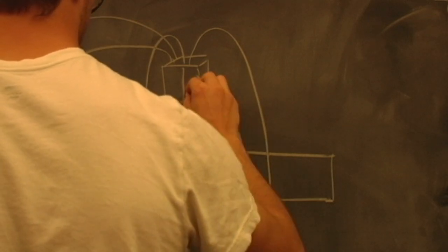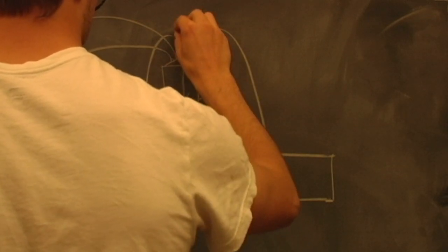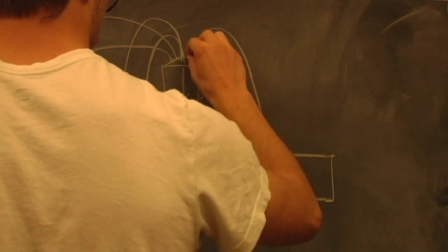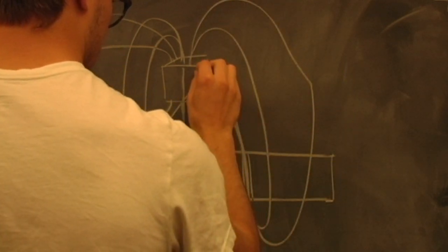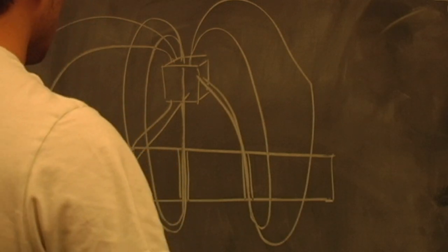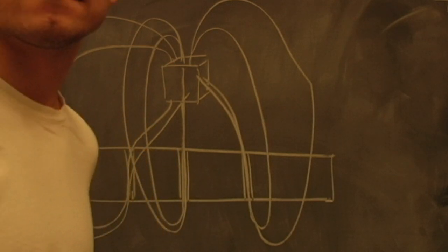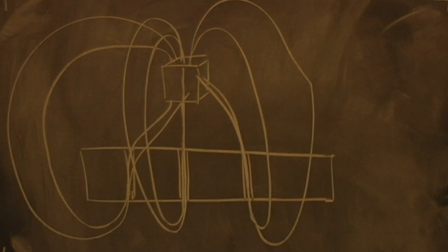The magnetic field can pass through the sample via these vortices. Each vortex carries a fixed unit of magnetic flux, which is given by Planck's constant divided by 2 times the fundamental charge. It's these vortices that pin our magnet in place. Without these, the magnet would just fly off the superconductor upon expulsion of the magnetic fields.